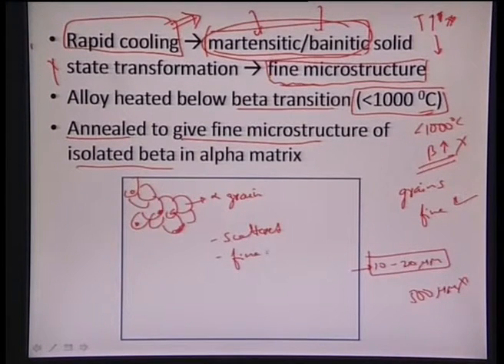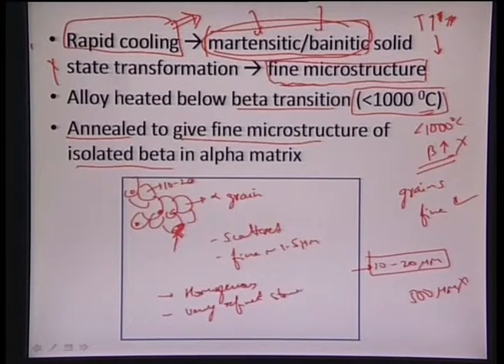Fine, it means it is to the order of maybe 1 to 5 microns or so. So this alpha is very fine because the grains themselves are around 10 to 20 micrometers. The beta, which is getting nucleated at high temperature, is again very fine, and it is scattered throughout. So we see a very homogeneous, very refined structure, and grains are to the order of 10 to 20 micrometers in diameter.